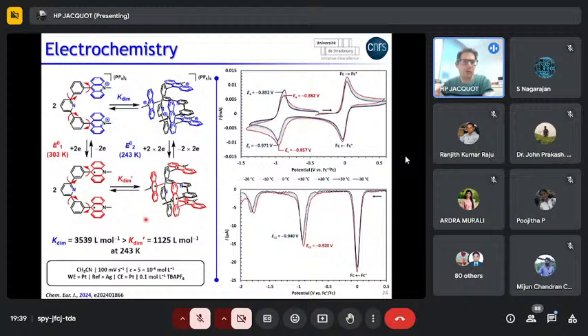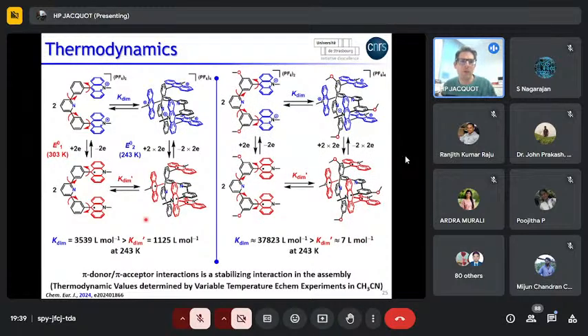What was done for the non-methoxylated tweezer can be done for the methoxylated tweezer. In this case, what we know from the thermodynamic parameters is that we have a favored binding constant for the methoxylated derivative in comparison to the non-methoxylated derivative. But what was very surprising to us is that when we look at the binding constant of the reduced species, we have a huge decrease for the methoxylated compound in comparison to the non-methoxylated compound.